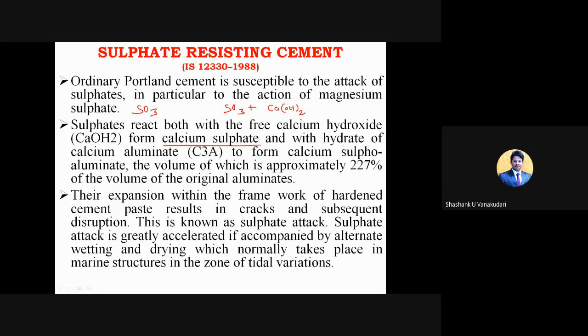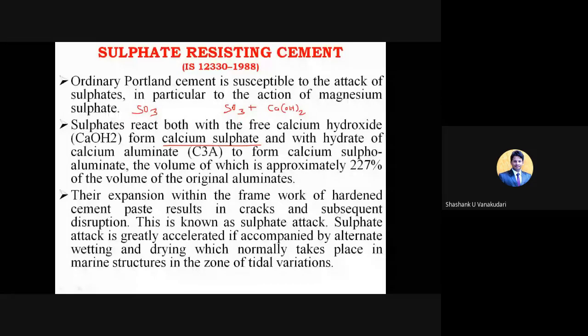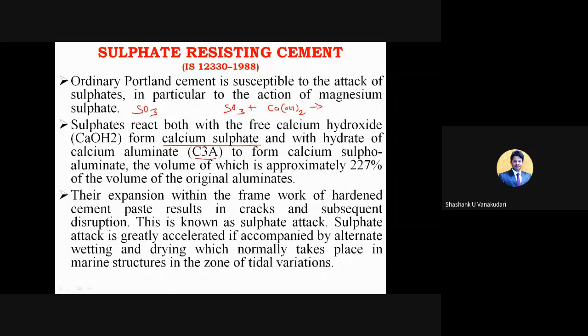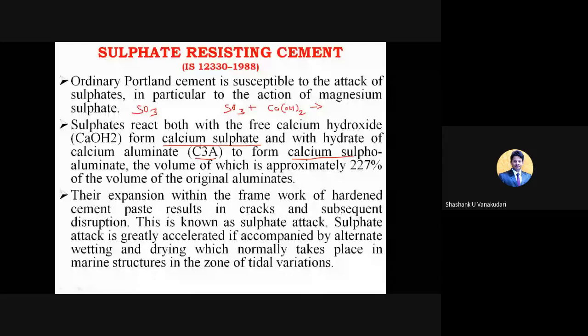It's nothing but what? The sulfates react with the calcium hydroxide, right? And form calcium sulfate. And again, with the hydrated calcium aluminate, that is C3A, tricalcium aluminate, that reacts with this calcium sulfate and forms calcium sulfoaluminate. Yeah, it's just like chemical reactions, and you just need to understand the basic concepts in words. No need to go into the reaction part. And here the volume is approximately 227% of the volume of the original aluminates. Okay, and their expansion within the hardened cement paste results in cracks.